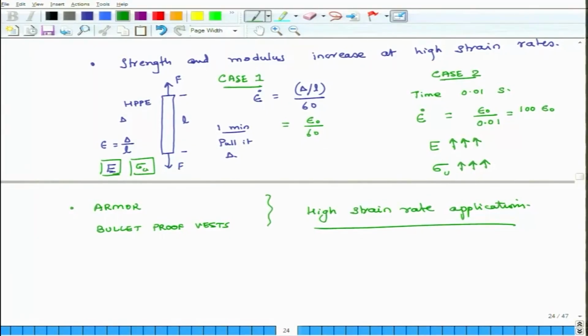But having said all this, they have a weak point: they start becoming very soft above 150 degrees centigrade, because they have a low melting point. I do not remember whether this is the exact number, but at not very high temperatures they start melting. So, if the overall temperature of the system is very high or even moderately high, we cannot use these types of fibers, but Kevlar you can use. Kevlar can go up to 500 degrees centigrade. This one maybe works around 100 degrees centigrade, but above that it will not work. But if at room temperature you want a bulletproof vest or some high strain rate application, this will do just fine. So, this is about HPPE fibers.